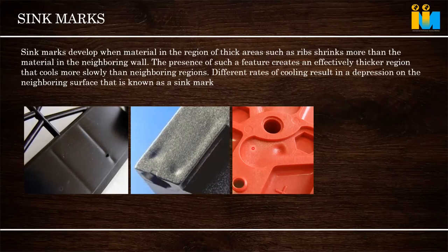If you are not able to give a cooling line or water line, they will drill and put a copper plug inside the cavity or core, so that heat gets extracted quickly and cools. That area cools quickly and a sink mark will not be formed. These are the techniques.